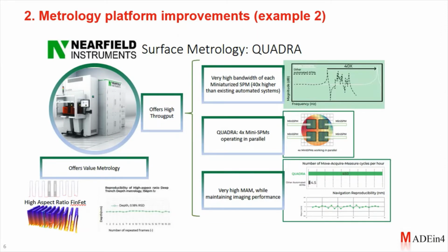Another example concerns scanning probe microscopy for metrology, which has been achieved by Nearfield Instruments. What they have done is to achieve a much higher throughput in that technology. The technology is used to measure top-down in a non-destructive way high aspect ratio devices, for instance, after etch. They have achieved this higher throughput by using a smaller, lighter scanning head, which has a way higher bandwidth, and at the same time, by integrating 4 of those scan heads into their tool. In total, this means that their improvement in throughput is about 100 times larger than what was traditionally the case.